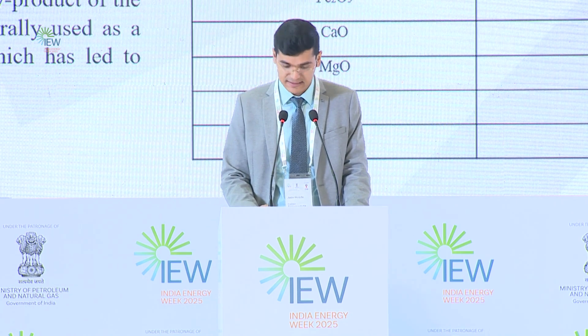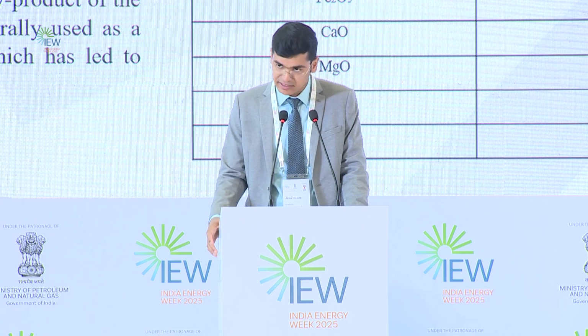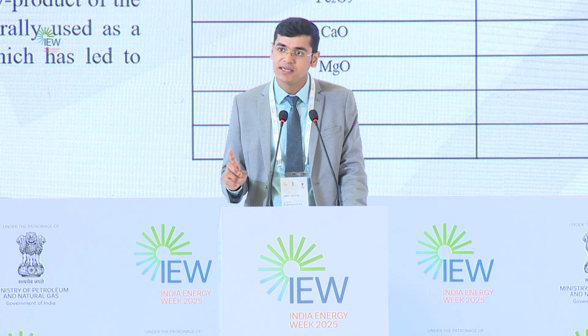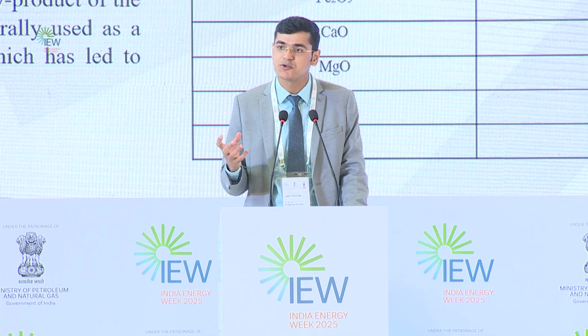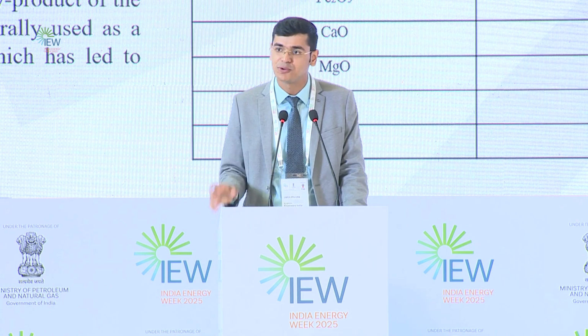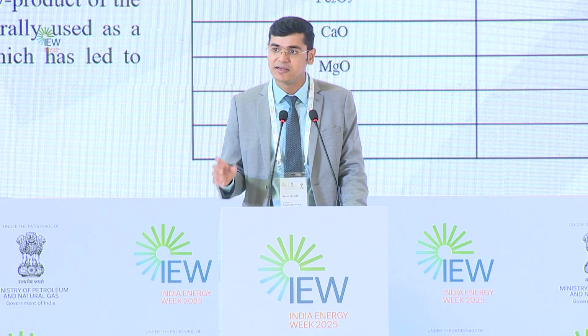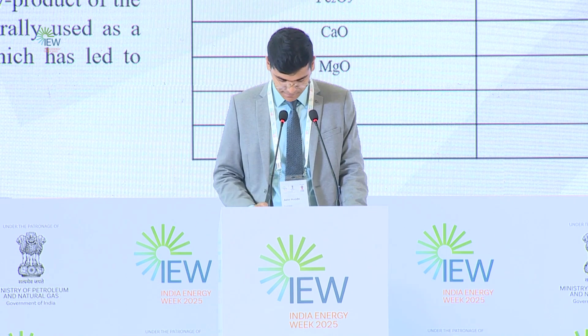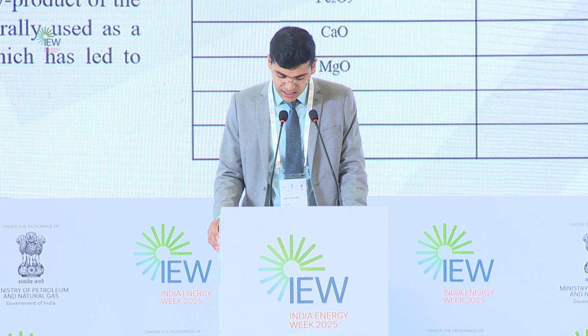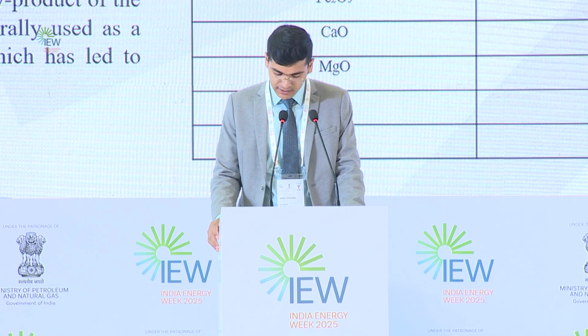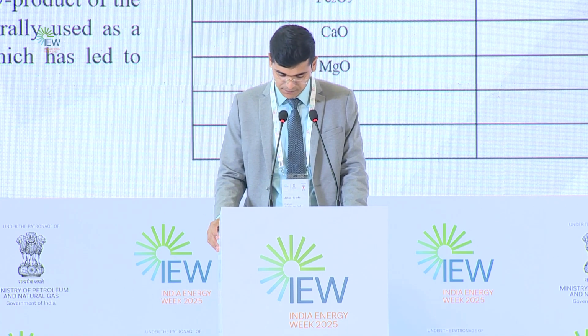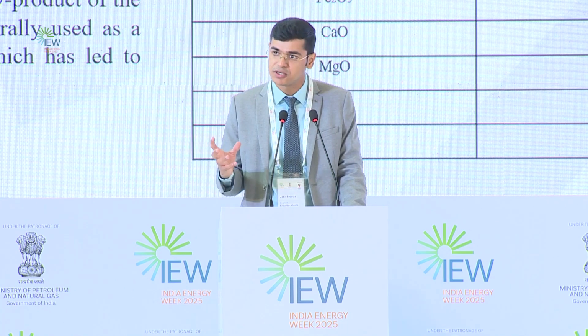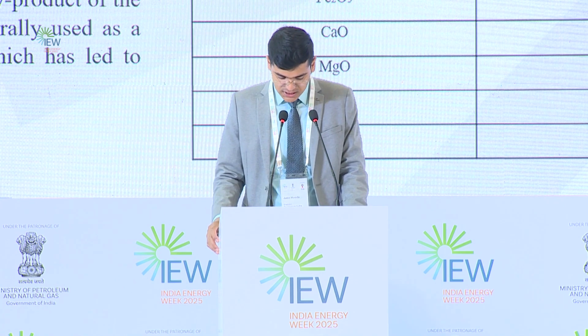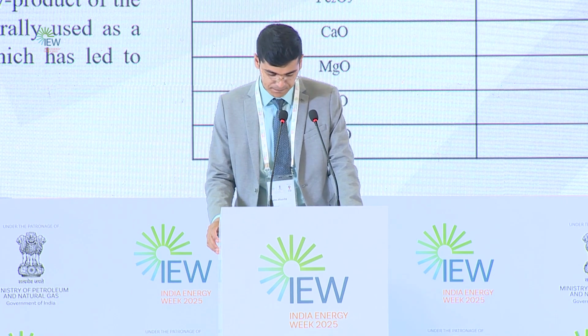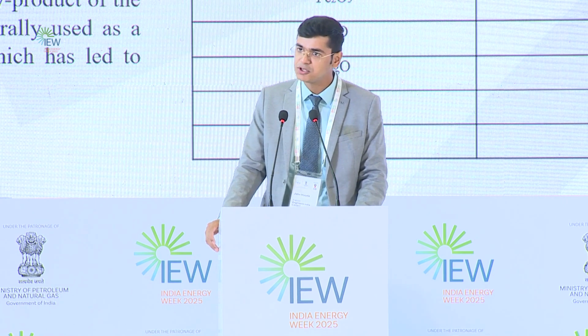So, the need for the present study: concrete is a composite material, as I have discussed. From 1 kg of cement production, we get nearly 0.6 to 0.8 kg of CO2. So you can very well estimate where the cement industry stands in carbon emissions. The sugarcane bagasse ash obtained from the combustion of sugarcane can be used as a partial replacement for cement owing to its pozzolanic nature, which provides strength to cement. SCBA is an abundant byproduct of sugar mills,